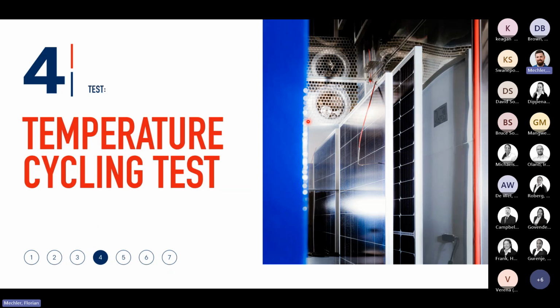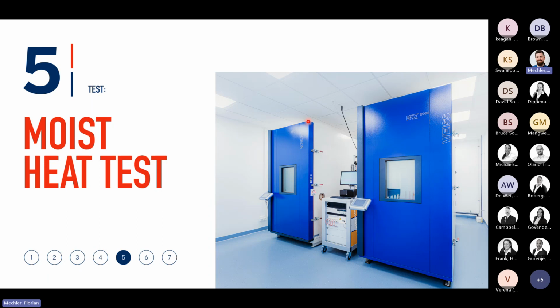Then we also have a temperature cycling test. It goes up to 80 degrees, and we try how it works in warm conditions, but it can also go down to minus 40 degrees to see how it works in very cold conditions. Then we also do a moist heat test to see if moisture can get into the module, and whether the module is produced very well, or whether there will be issues from moisture coming into the modules.